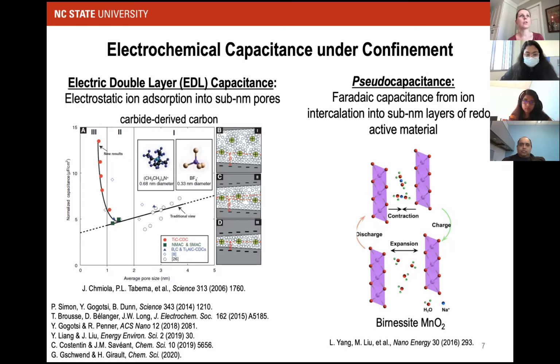But typical numbers would be, for a double layer capacitor that's purely double layer with a lot of the functional groups taken off, about 1 million cycles. A high energy density capacitor that includes some redox active functionalities, or a lithium-ion capacitor, is about 600,000 cycles. And then lithium-ion batteries are another order of magnitude down. So yeah. And one last follow-up question, Prof.